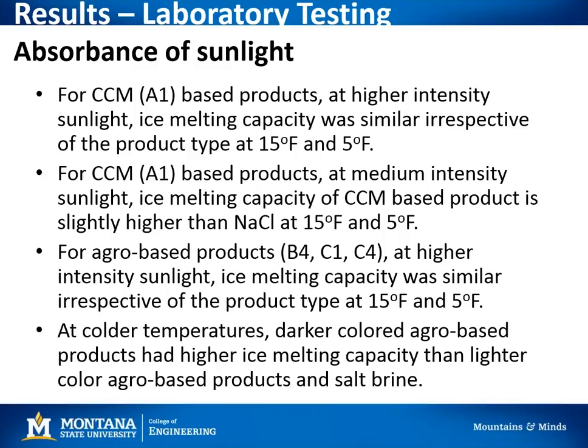So for the complex chloride mineral-based product, with the medium intensity sunlight, the ice melting capacity was slightly higher than for the salt control. While for agro-based products with the higher intensity sunlight, the ice melting capacity was similar regardless of product type, regardless of temperature. And one of the interesting findings that we were hoping to tease out of this was that at the colder temperatures, the darker colored agro-based products had higher ice melting capacities than the lighter agro-based products. And that likely has to do with the albedo factor, and that darker products will absorb more light than the lighter ones. This test, as I mentioned, was the first time we had conducted this.